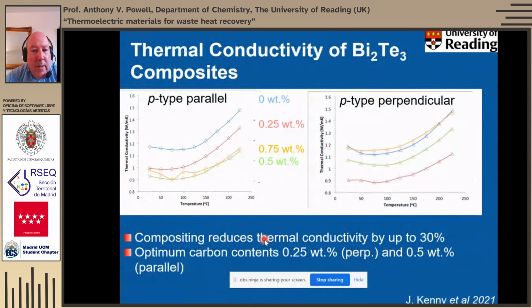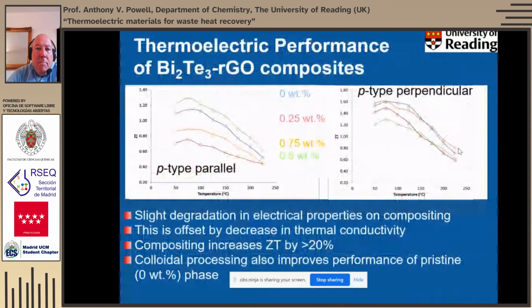And what that achieved is it allows us to have significant reductions in the thermal conductivity. I mentioned the anisotropy of bismuth telluride, so these are measurements made parallel to the pressing direction and perpendicular to the pressing direction. But you can see that in both cases, as we add some reduced graphene oxide into our material, we get quite significant reductions in thermal conductivity, in fact up to about 30% reduction. We find that the optimum content, for the thermal conductivity at least, depending on which direction we're measuring, is either 0.25 or 0.5%.